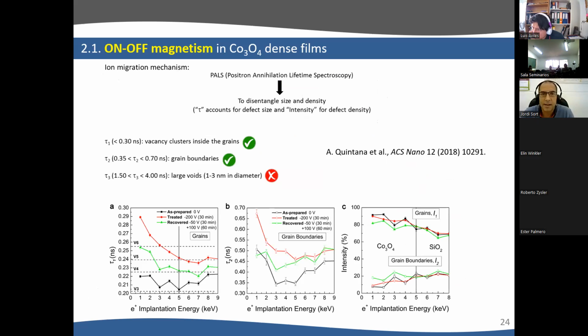Now, to further understand and complicate things a little bit, we sent the samples to our colleagues in Rossendorf, where they do positron annihilation lifetime spectroscopy. I don't have time, and I would even say I don't have the expertise, to give all the details about this technique. But basically, this technique is used to characterize vacancies. What you do is irradiate the sample with positrons, and then you measure the time it takes for the positrons to be annihilated, so you are sensitive to vacancies and other defects. If the lifetime is very small, it corresponds to vacancies inside the grains. If the lifetime is a bit larger, to the grain boundaries, and if it's very large, up to 4 nanoseconds, it means really voids, like porosity. But we don't have this.